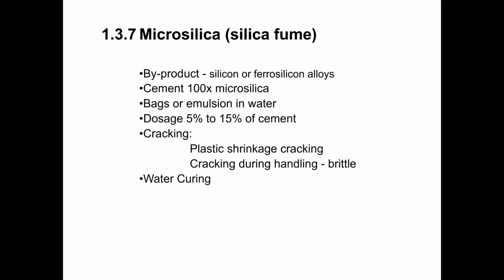The key thing to keep in mind if you're using microsilica as an emulsion is that since it doesn't dissolve, it will settle out of the water. And so whatever container the emulsion is being stored in, that emulsion needs to be agitated. So it needs to have stirring paddles. It needs to have some way of agitating that material so that the silica fume doesn't settle out, so that we have a given proportion of silica fume throughout the volume of the water that it is suspended in.